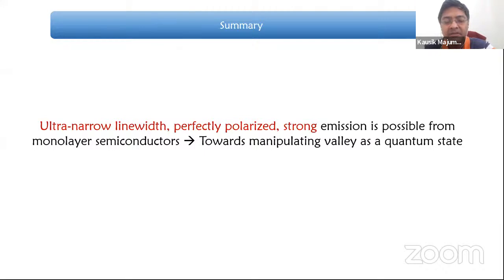So, but there are, of course, certain states where we do funnel these K excitons into sort of strained trapped states close to the K valley. So for those cases, I think it is possible. In fact, we have some recent data on moiré superlattices which show very high polarization, not 100%, but very high polarization. But I cannot comment on those states which are arising from somewhere else in the Brillouin zone, because they have nothing to do with the K or K prime valley. And so accordingly, you don't know whether it's going to have the right symmetries for these